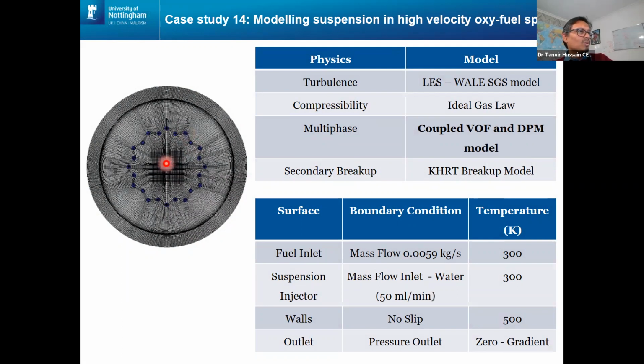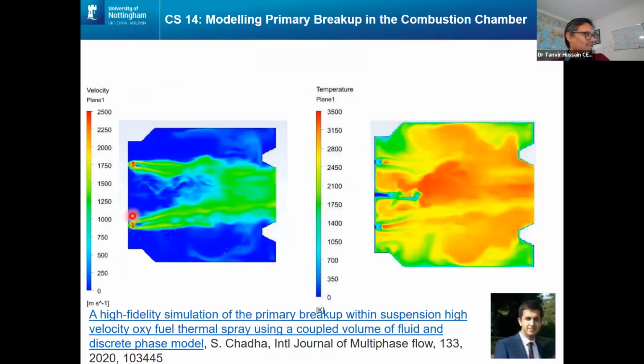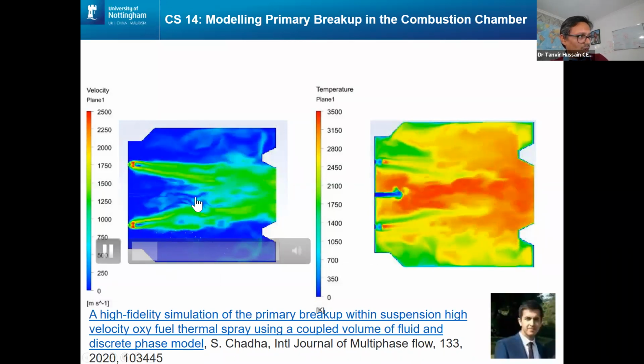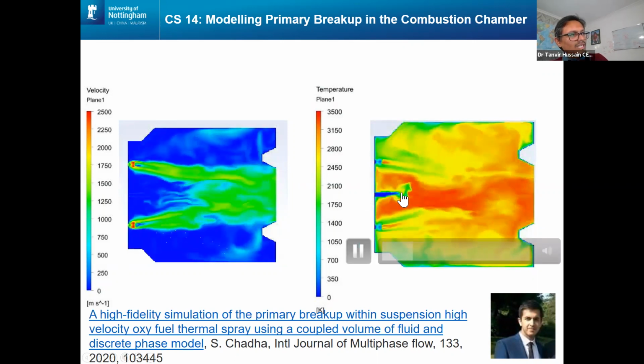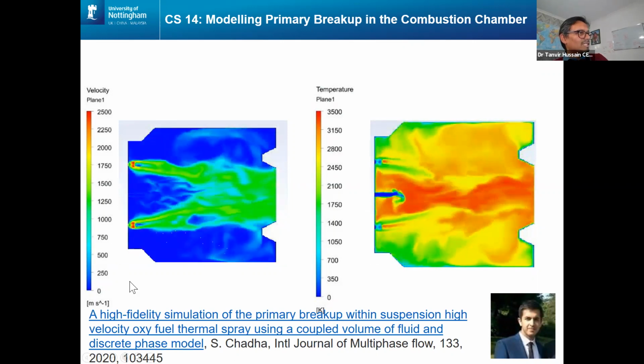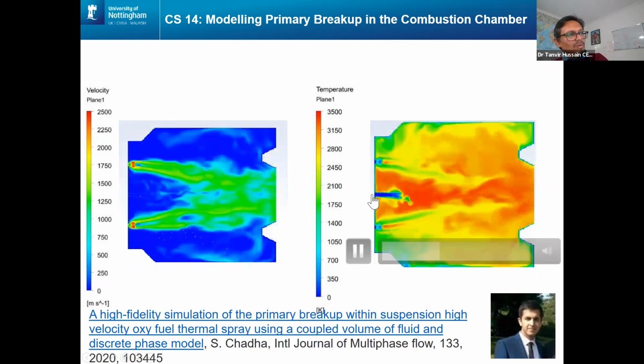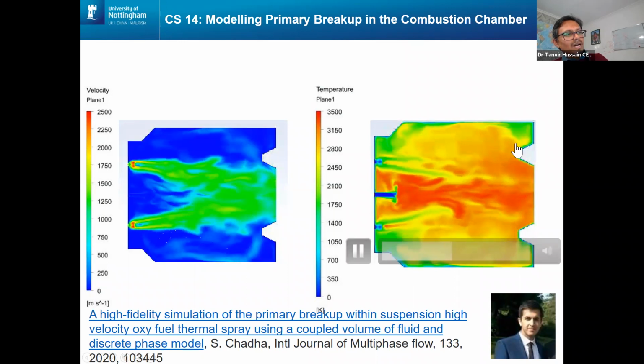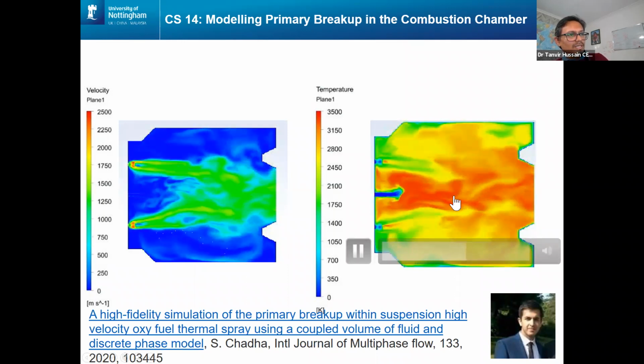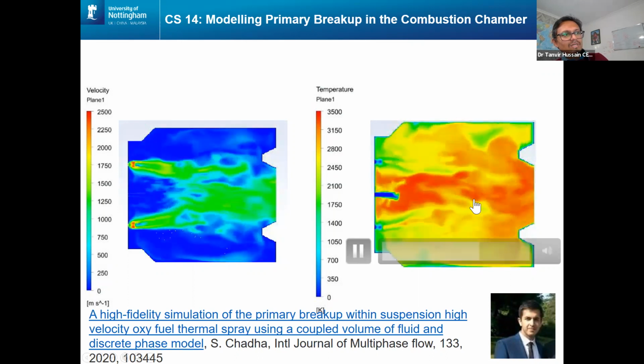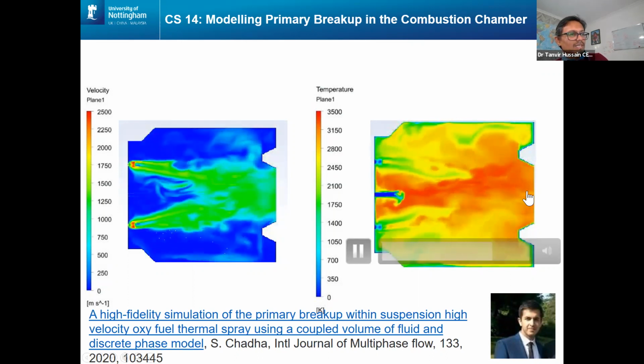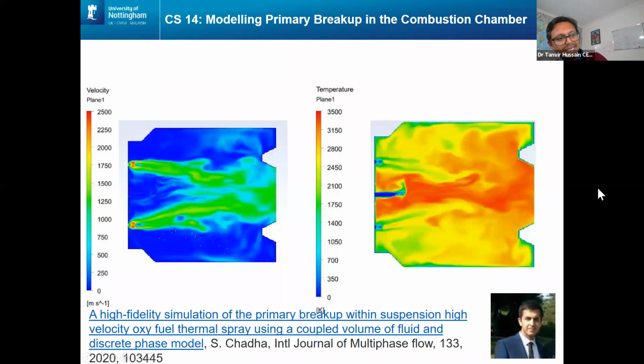This was a multi-phase model where we have a coupled volume of fluid with DPM, the discrete particle modeling. And let's hope this video works for me. What we're doing here is a combustion chamber where oxygen and hydrogen come in and combust, and at the center we are injecting suspension. That was Sunil's work, and that's velocity and that's temperature. You can see when we inject the suspension how this turbulent environment breaks it down, because on this side I have the nozzle. All of these suspension particles are accelerating towards that nozzle and getting deposited on that end.